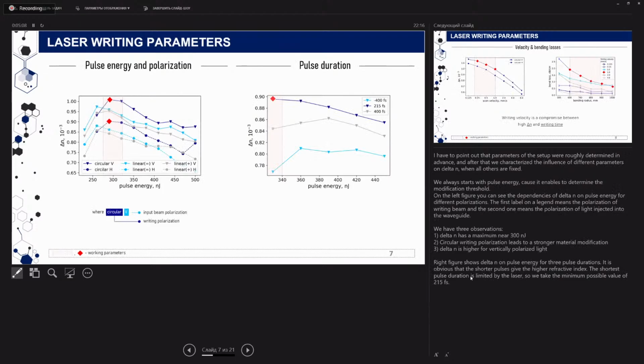I have to point out that parameters of the setup were roughly determined in advance, and after that we characterized the influence of different parameters on delta n when all others are fixed. We always start with pulse energy because it enables us to determine the modification threshold. On the left figure, you can see the dependencies of delta n on pulse energy for different polarizations. The first label on the legend means the polarization of the writing beam, and the second one means the polarization of light injected into the waveguide.